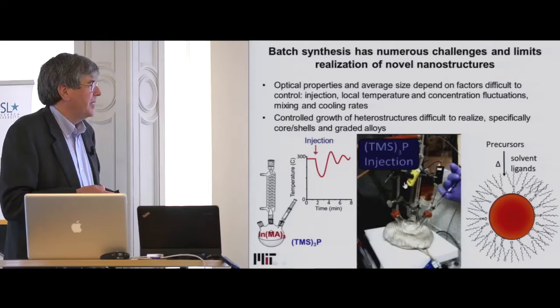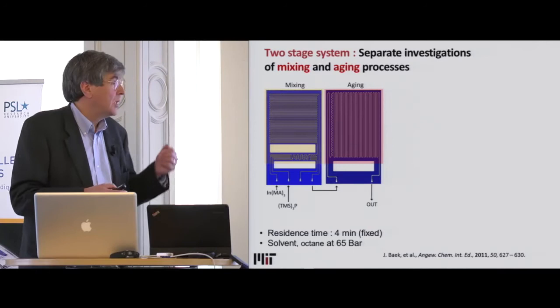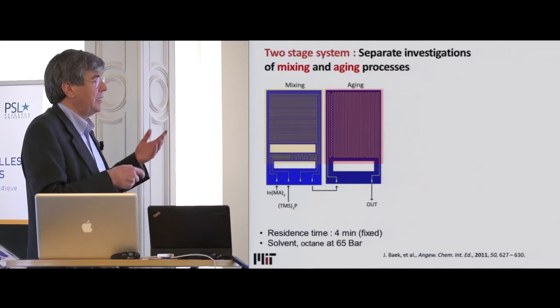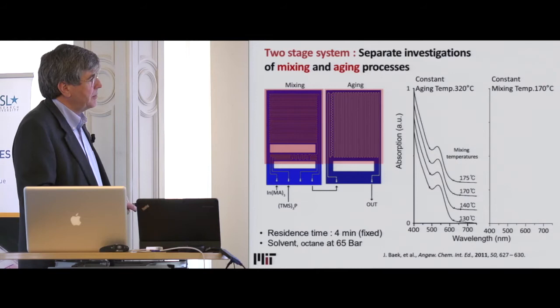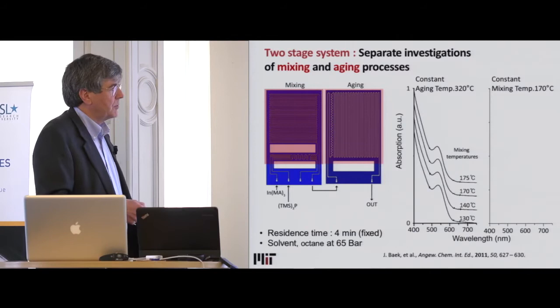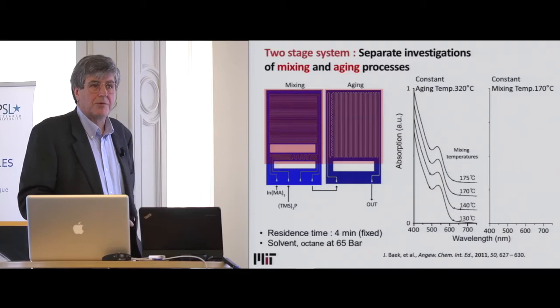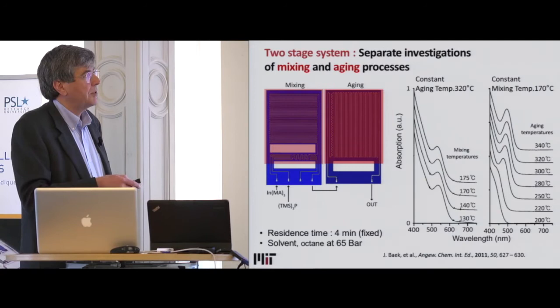Why not do this in microfluidics where you can actually control conditions? You can then begin to answer questions that people have had: what is important in this process? Is it an issue of mixing? Is it an issue of how long you have the crystals sitting around? You can separate those effects because you can first study the mixing temperature and then the aging temperature. Looking at absorption spectra — what's really important is the resonance structure, which determines what you get in terms of emission. There's really no difference with different temperatures of mixing. However, if you change the aging temperatures, there is a significant effect — the higher temperatures you can go, the better. We think this is because you form lots of small nuclei that then have to fuse and grow into larger nuclei to ultimately form the quantum dot.